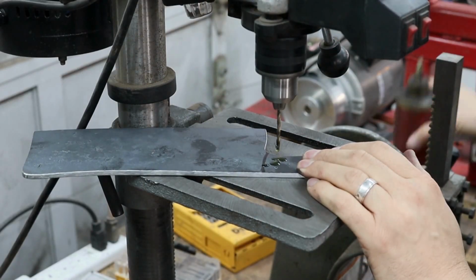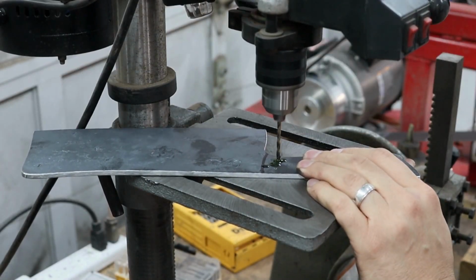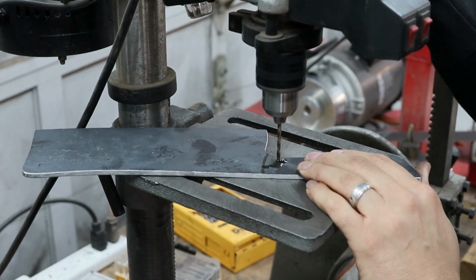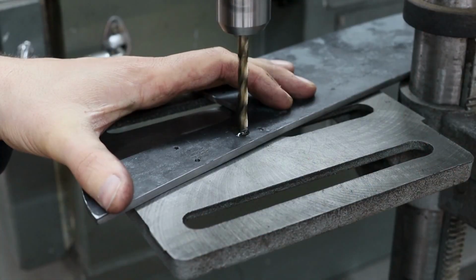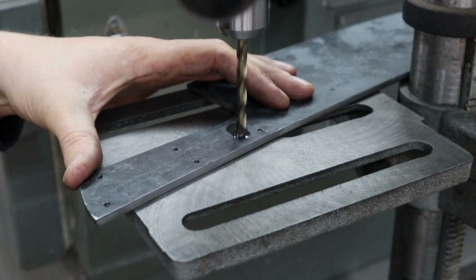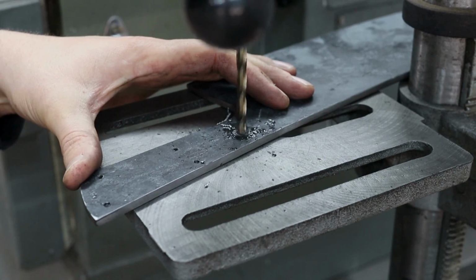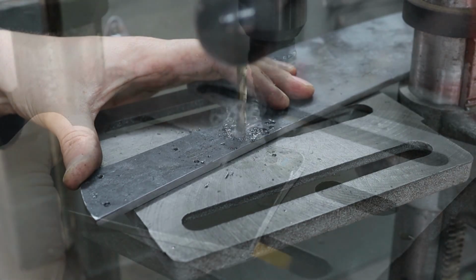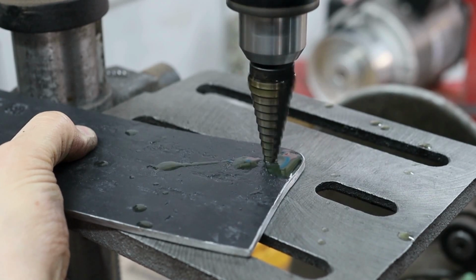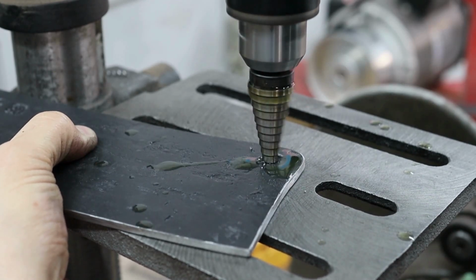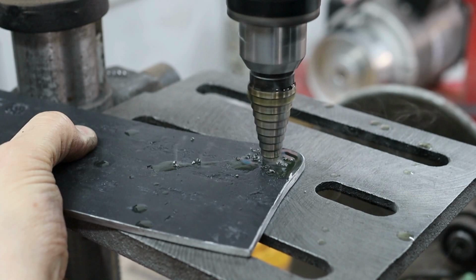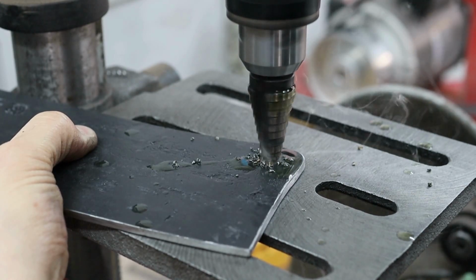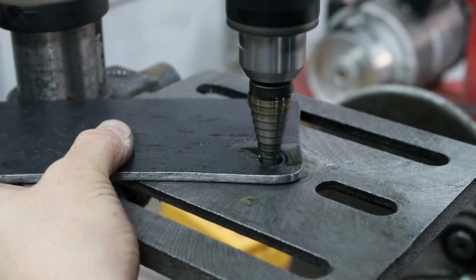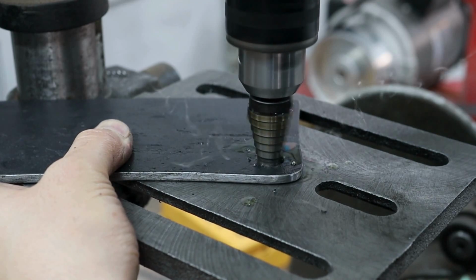I drilled out 6 holes for handle pins and the rest for weight reduction and to allow the epoxy to bond all the way through from one scale to the other. I like using this stepper drill bit rather than using a large drill bit and then chamfering the edges. I think this gives a much cleaner finish. It almost sort of rounds over the edge as opposed to creating like a 45 or a 30-degree chamfer.